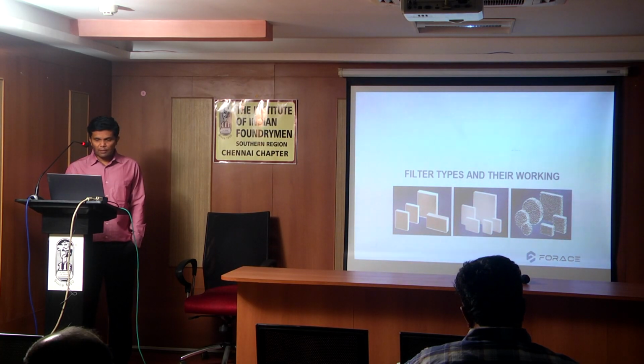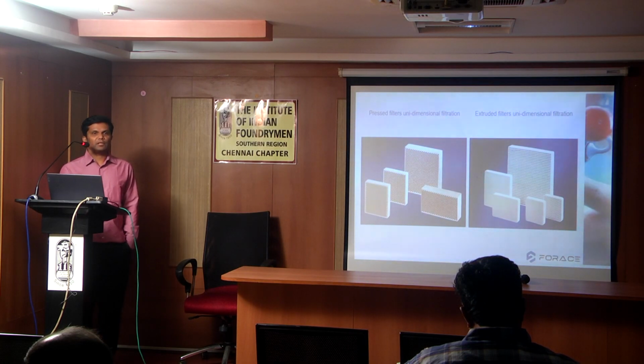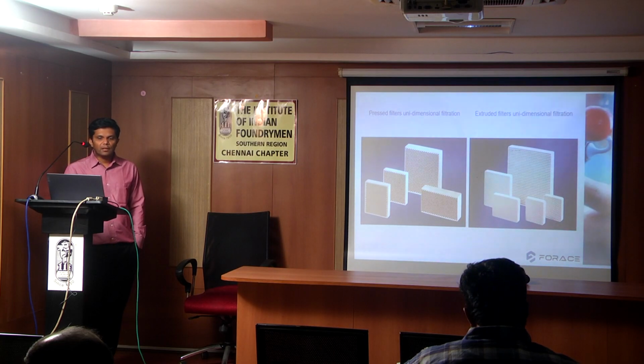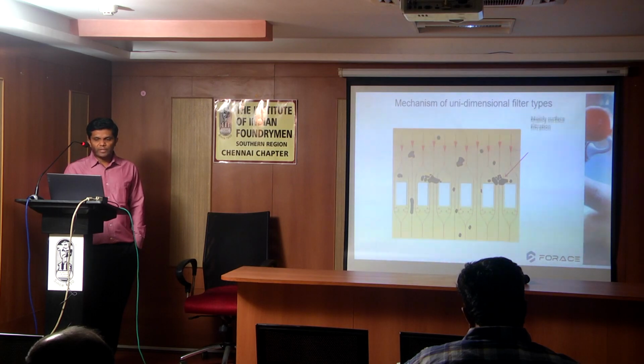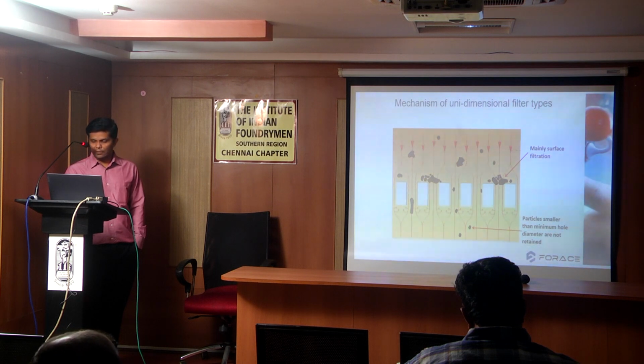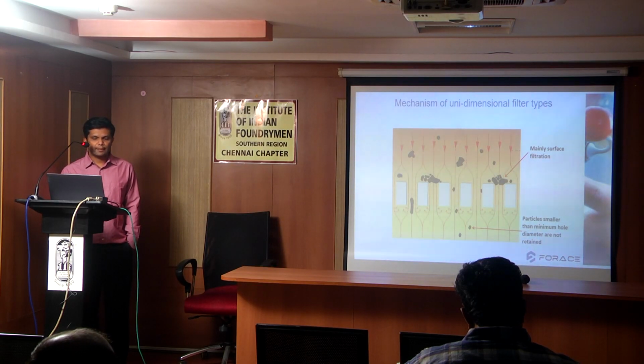So I will tell something about the filters. These are the familiar filters across various foundries. These are the pressed or extruded filters. Their working philosophy is like this. They have specific holes, and if the metal or inclusion comes greater than the diameter of the holes, then those inclusions or slags will be trapped on the surface. If the inclusions or slag are smaller than the holes, then the slag will go inside.